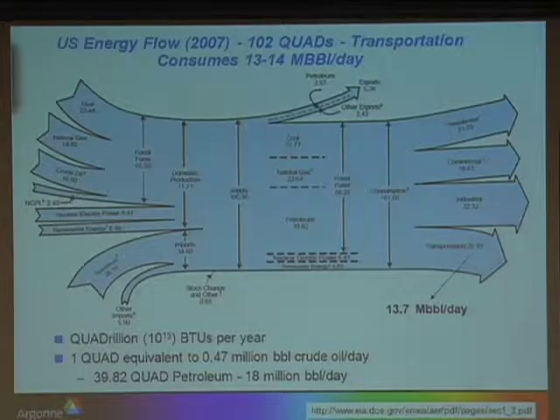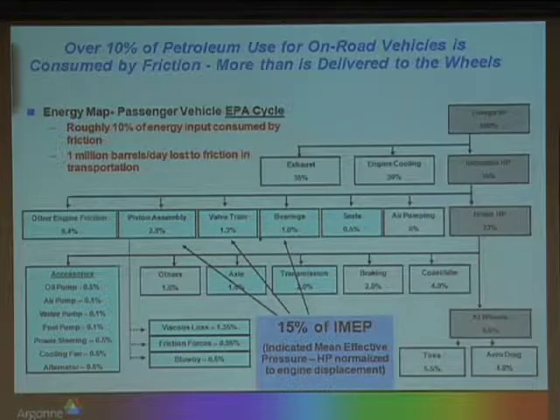Of that 14 million barrels of oil used per day, about 11 million barrels is used for on-road transportation, for passenger vehicles, for light trucks such as SUVs, as well as the heavy commercial trucks. And of that 11 million barrels per day, about 10% of that petroleum is consumed by mechanical friction within the engine and the driveline. So you're looking at about a million barrels per day that's just lost due to friction. And so there's a significant opportunity to reduce friction in order to conserve petroleum.